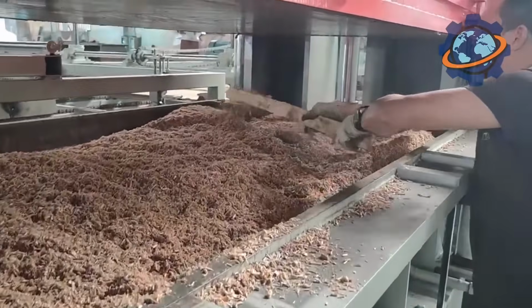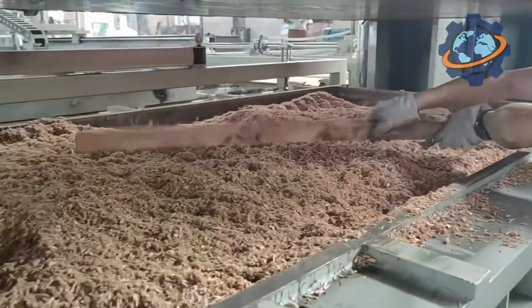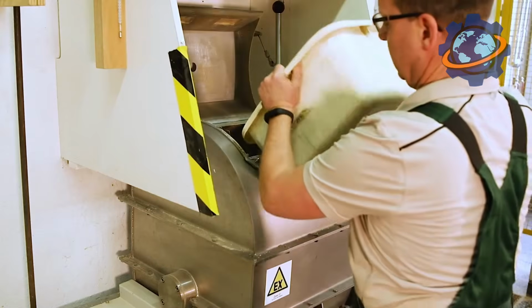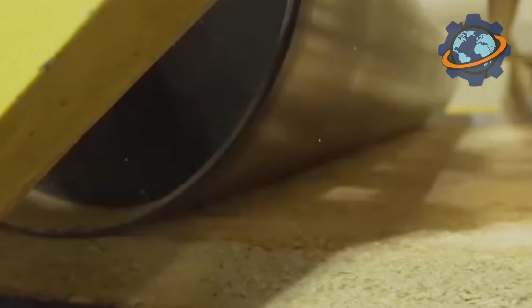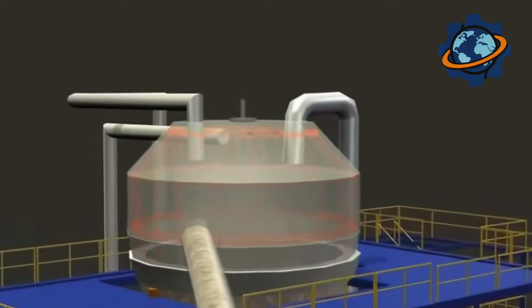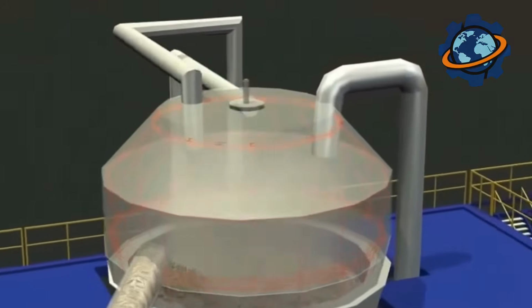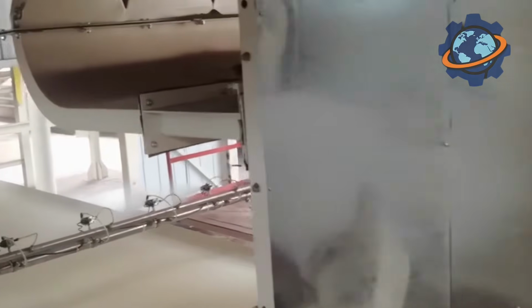If the chips are over-dried, they will not be properly saturated with glue. If they remain too moist, during hot pressing, the excess water vapor can rupture the board from the inside, forming defects. The dried chips are not uniform in size. To create the correct 3-layer structure of the board, they must be sorted. The chip mass passes through a system of mechanical screens or air separators.